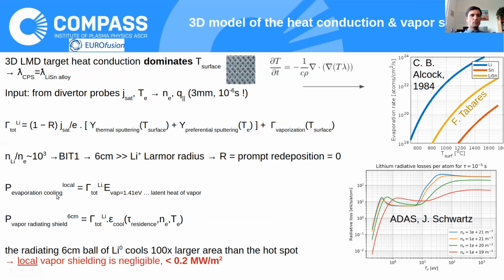The evaporation cooling is either local, which is given by the latent heat of vapor, because each particle just loses 1.4 electron volts of energy, plus vapor radiative shielding, which should be quite high, because this cooling energy per each released atom is pretty high. It goes from tens up to hundreds of electron volts, depending on the electron temperature of the incoming plasma.